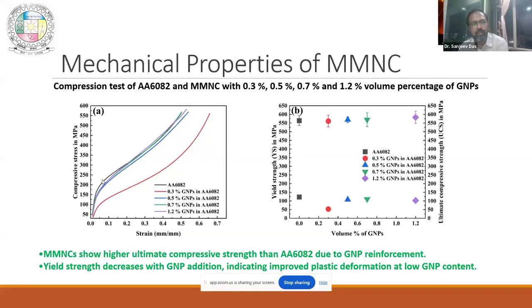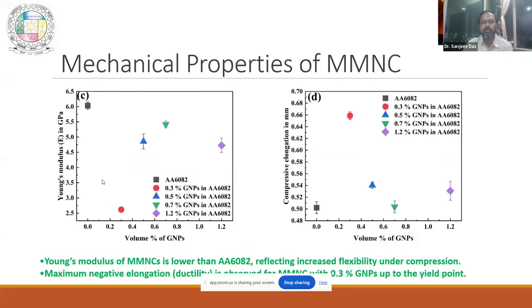Other than tensile testing, we again did compressive testing, and these are the compressive test results. In the compressive test results, we didn't find that UTS is much better than your tensile strength. It is either the same or it is dropping. You can see the Young's modulus has dropped, meaning it is not showing that stiffness. In compressive load, it is just showing something different. So this is very interesting for us, and we are trying to understand exactly why it happens. But we understood one thing: if you are making nanomaterials, it will give you good tensile strength, but for compressive strength you should go for micro level reinforcement, not nano level.